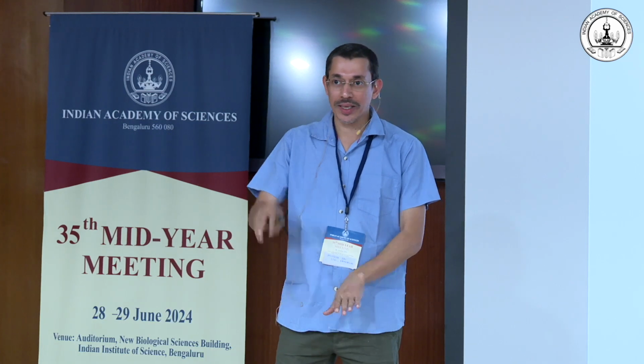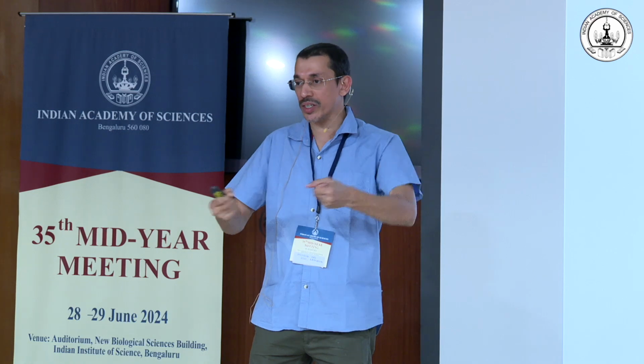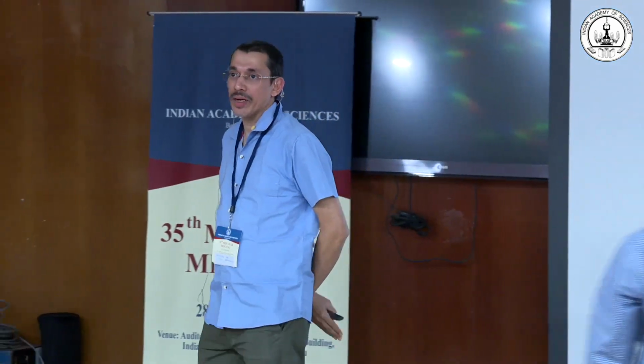But van der Waals, once they form, is a very strong interaction. You cannot change anything. In fact, they are very robust because the area is quite large. Unless you do this pressure experiment, or you can give some uniaxial strain and those kinds of things. But yeah, the intercalation might be something that can be done. Please go ahead.